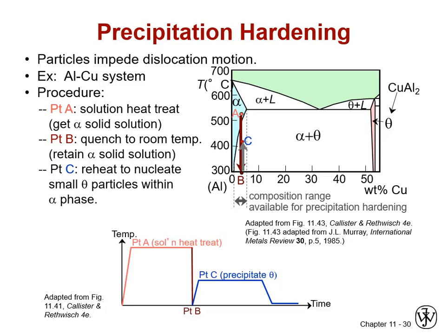We're going to let its thermodynamic drive to associate with itself actually volumetrically form some CuAl2, but we're going to make sure that the edges of those precipitates stay coherent with the parent lattice. That means they're going to be strained off of the positions they'd really like to assume, and we're going to introduce strain energy into the lattice the same way a solid solution does, the same way the martensitic transformation does, but not quite so much, but enough to give a lot of strength.